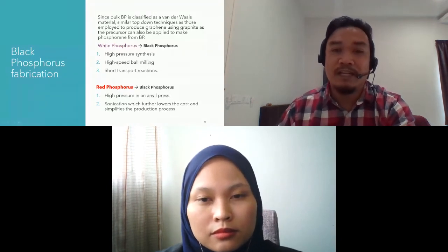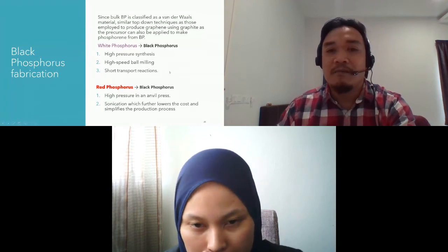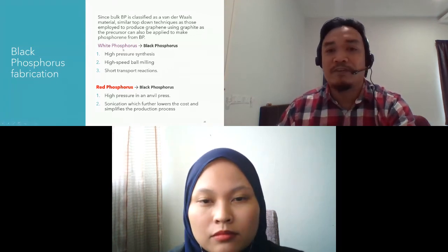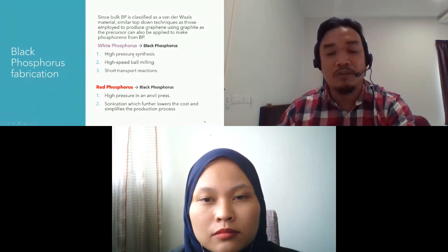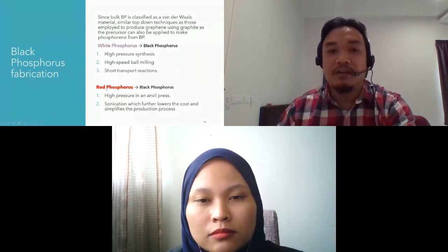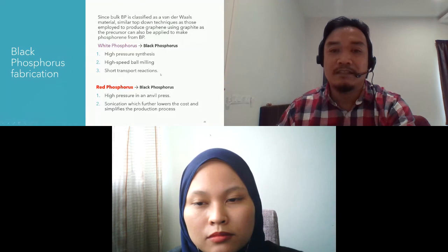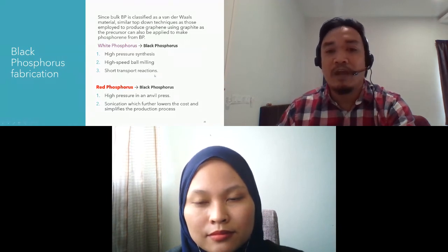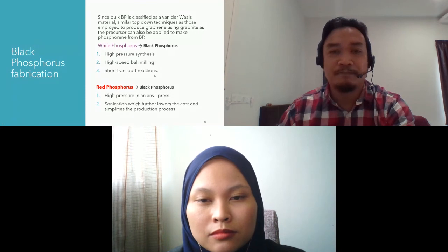The first one is by using white phosphorus, which is the easiest one. By using white phosphorus, we can have black P by using high pressure synthesis, high speed ball milling, and short transport reactions. But as I said just now, white phosphorus is very dangerous. So we go to the other way, which is red phosphorus into black phosphorus. To obtain BP from RP, we need high pressure and also sonication, which further lowers the cost and simplifies the production process.